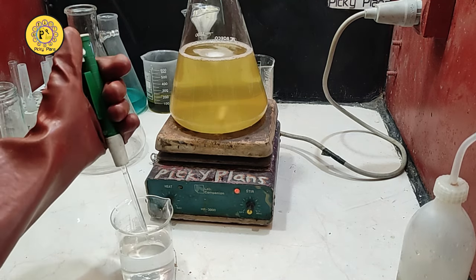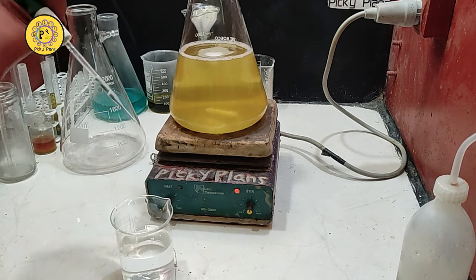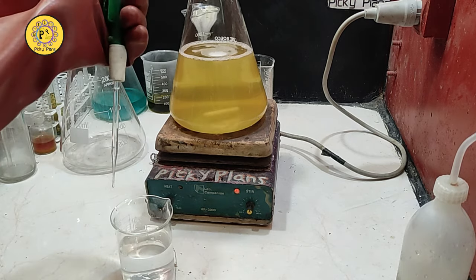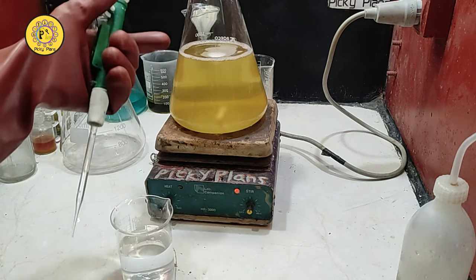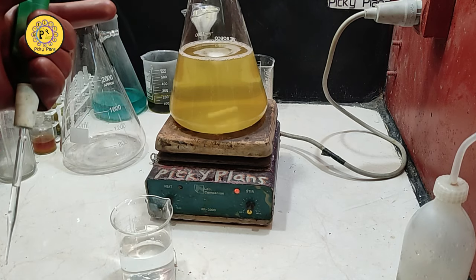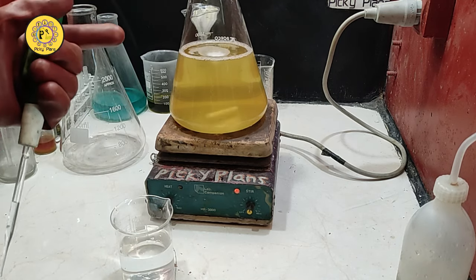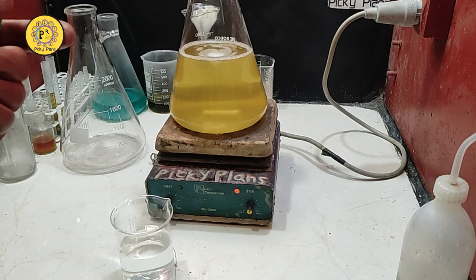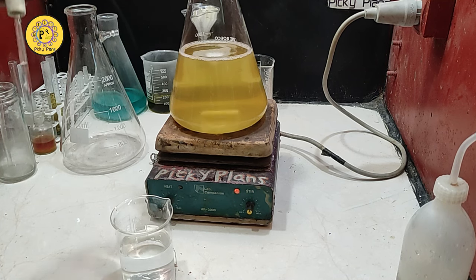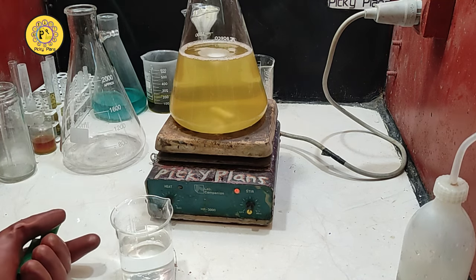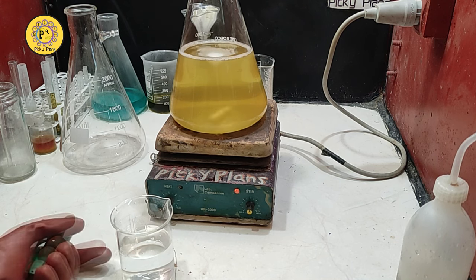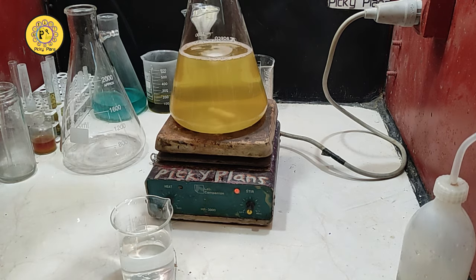Around 5% hydrochloric acid being added to the solution, to the point where the solution pH should be between 5 and 6. We don't want to go lower than 5, and 6 is good enough. So I start adding dilute hydrochloric acid.